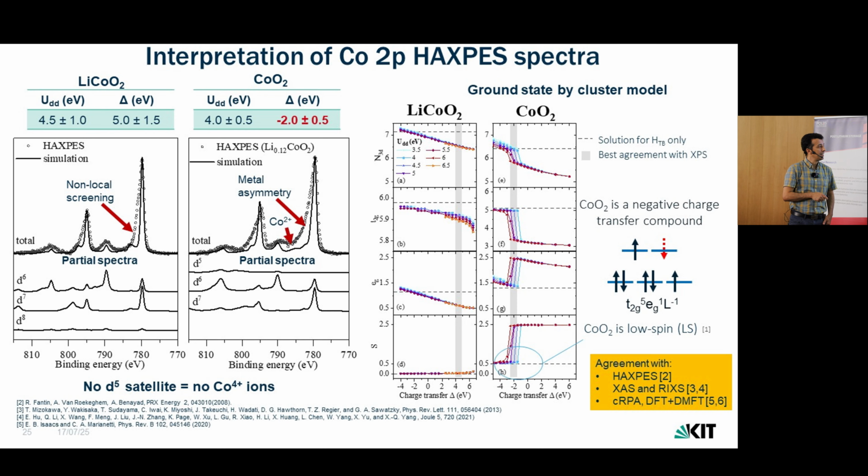So we can see that when we de-insert lithium, indeed, we remove an electron from the structure. But immediately, as soon as we remove this electron, the oxygen draws back an electron to the eg state. That's what we call negative charge transfer, and in this way the oxygen compensates this charge. So at the end it is not cationic or anionic, it is more a collaborative and self-regulating process.